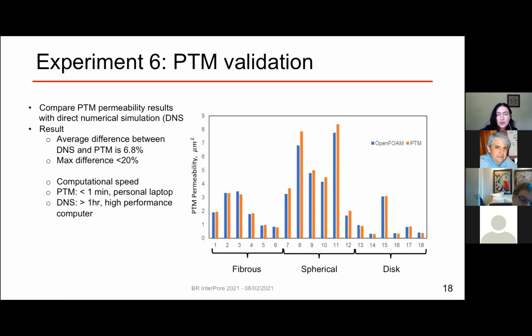between direct numerical simulation and our own in-house method. The maximum difference is under 20%. Again, it happens at low porosities where we knew we had some issues. But look at the computational speed. For the pore topology method, we need less than a minute on a personal laptop with this, whereas the equivalent computation with direct numerical simulation is more than an hour on a high performance computer.